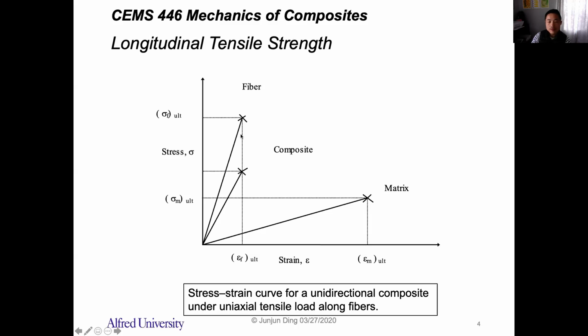So this is the longitudinal direction. And you'll see that the maximum strain that can be applied to the composite and the fiber is the same, right? Because if the fiber fails, that means the composite fails, right? So that's why the maximum strain for the fiber and the composite is the same, the ultimate strain of the fiber. While the matrix has a much larger ultimate strain, right? That is usually true for most of the composites, especially for polymer matrix composites.